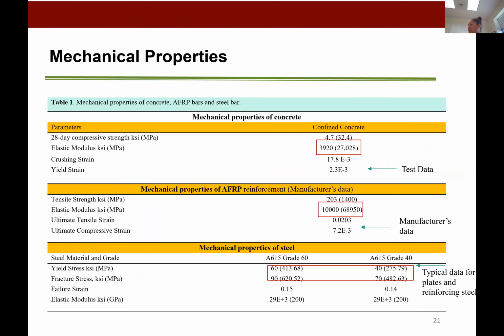So if we look a little bit at our mechanical properties, we know that we're just using about 4,700 psi strength concrete, so no high strength concrete, with typical elastic modulus for the concrete as shown, and just using basic properties of the concrete. We pulled the manufacturer's data to mimic the AFRP bars with 10,000 KSI for the modulus of elasticity, and looking at ultimate strains of about 0.02, so about 2% strain. For the mechanical properties of the steel, we're looking at grade 60 as well, and then the yield stress and fracture stress for the plates, and then the reinforcing steel.